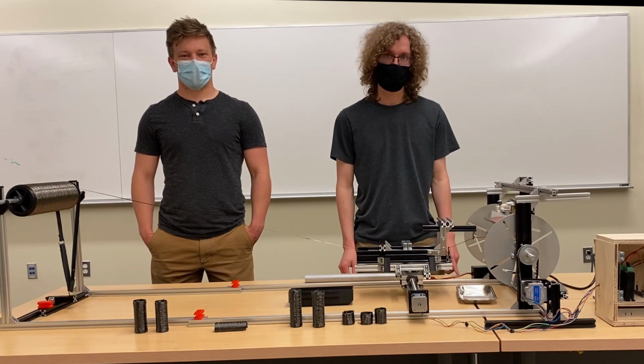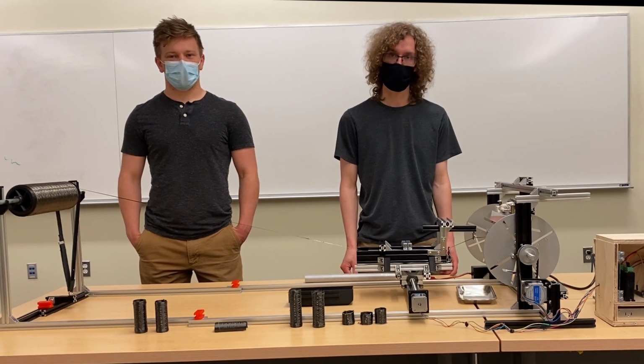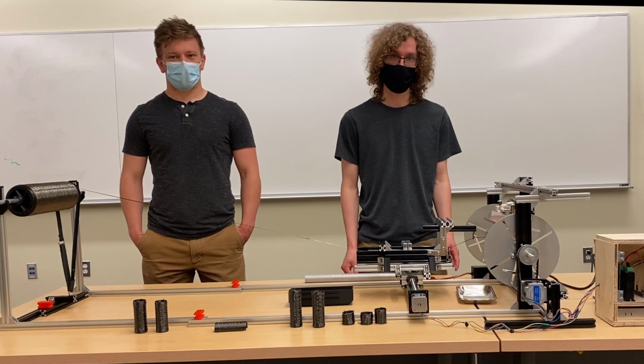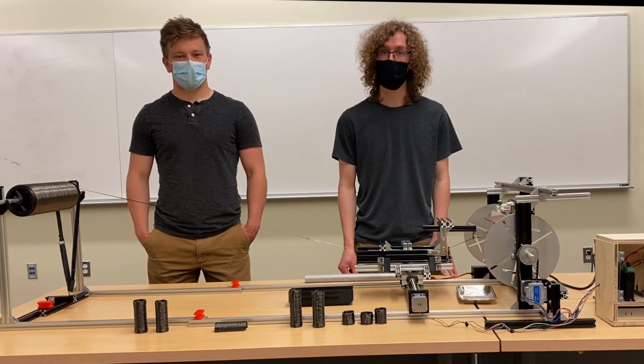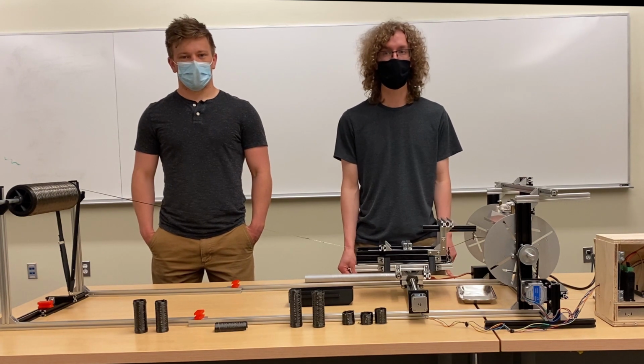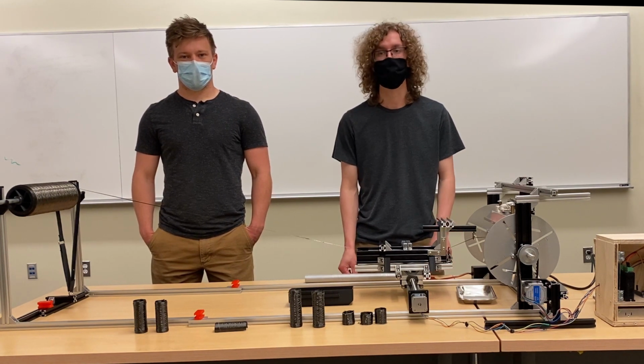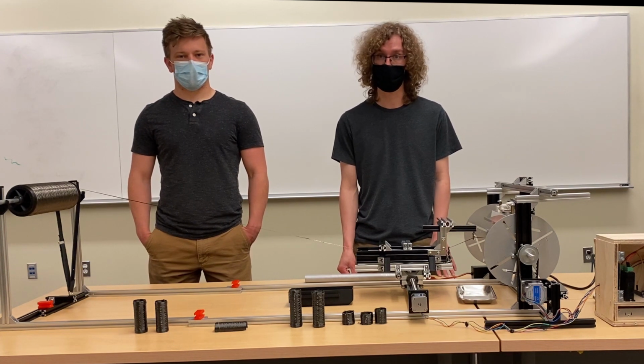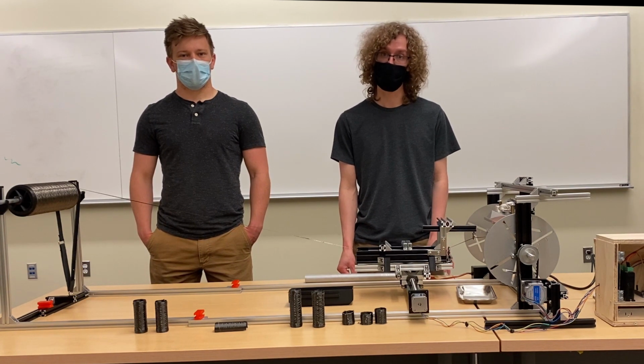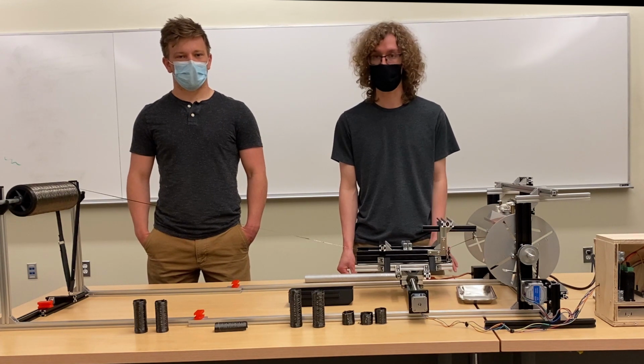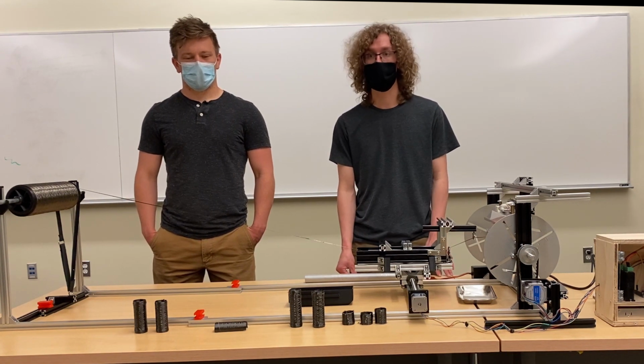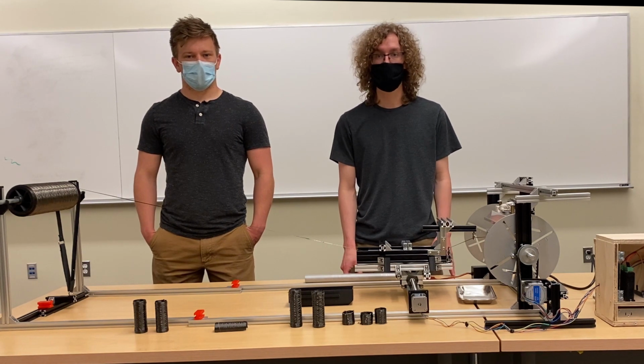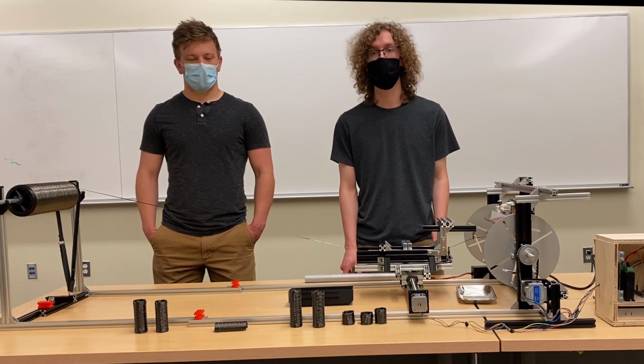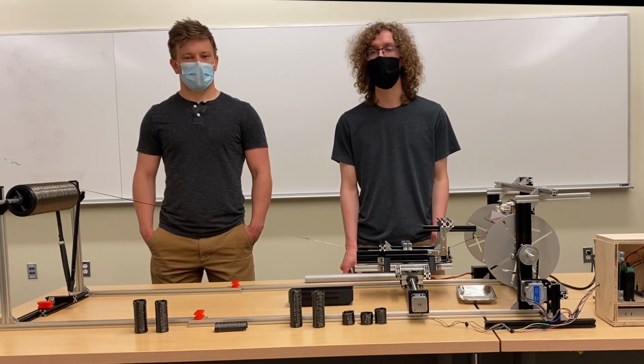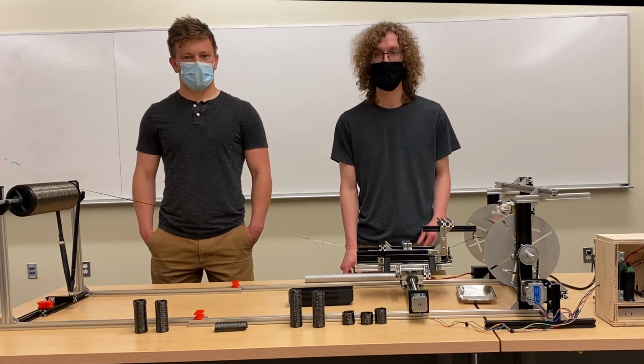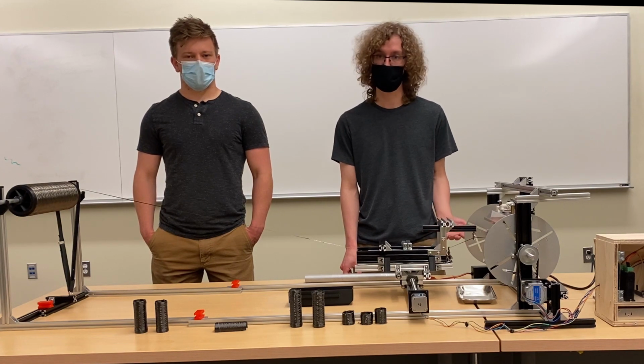Ultimately, this project demonstrated the feasibility of using the self-curing formulation of DCPD in the filament winding process. We were able to manufacture carbon fiber composite tubes considerably faster than the current industry methods. Additionally, we demonstrated the feasibility of both resistive heat and infrared radiation curing methods in this process. In conclusion, the IR heating method was the most feasible curing method we explored due to the consistency of resin distribution and the ease with which IR heat sources could potentially be installed in any existing filament winders in industry.